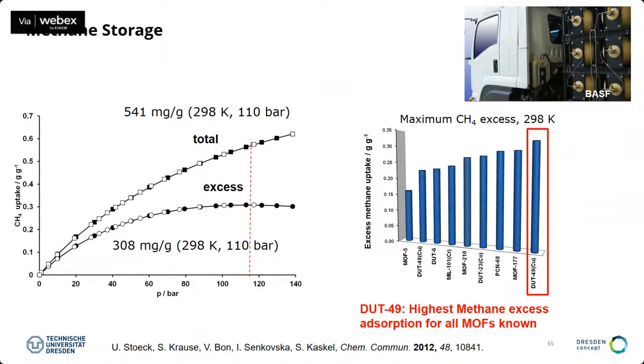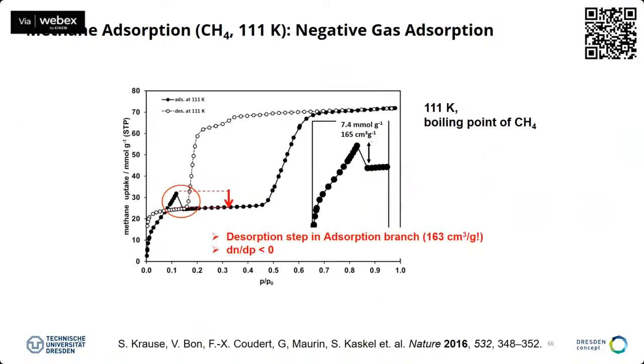And that was very interesting for applications. But we were also interested to get a deeper understanding why this material is a record leader, why it is so special, why it can take up so much methane. And therefore, we started to record methane adsorption isotherms at the boiling point of methane, 111 Kelvin.